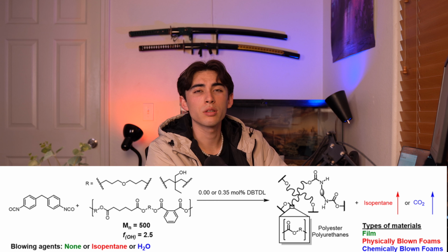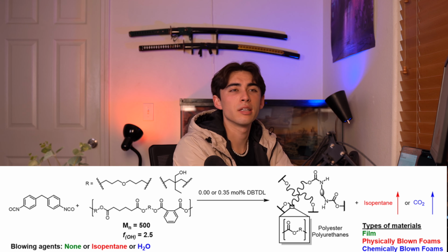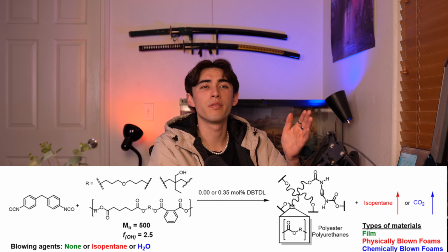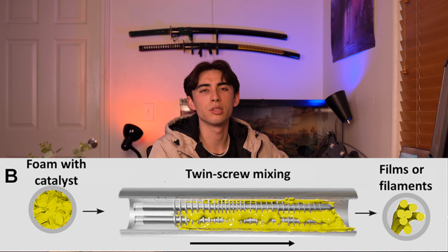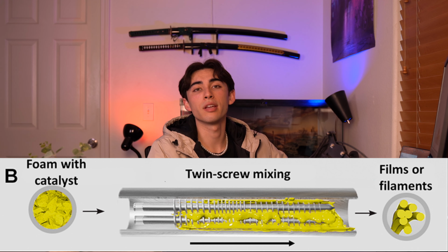This study first took methylene diphenyl diisocyanate and a commercially available polyester polyol and synthesized a polyurethane foam using both physically blown and chemically blown agents. The foam was synthesized with a small amount, roughly 0.35 mole% of dibutyl tin dilaurate, or DBTDL, which was the catalyst. Both the PU foams and films exhibited stress relaxation at elevated temperatures using the dynamic carbamate exchange reactions. The PU foams were reprocessed using twin screw extrusion to remove the gaseous filler. The remaining polyurethane could be used to produce filaments or films that could be retested for stress relaxation. These findings should hopefully enable the bulk reprocessing of commercial polyurethane waste.